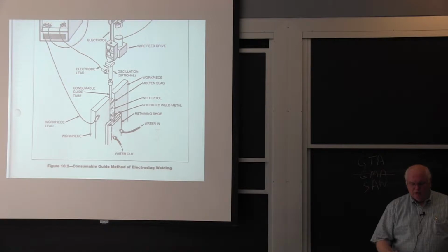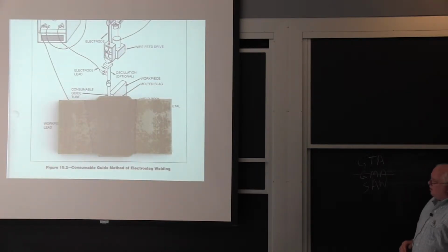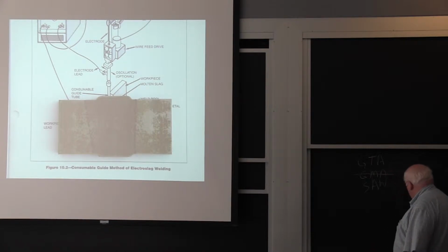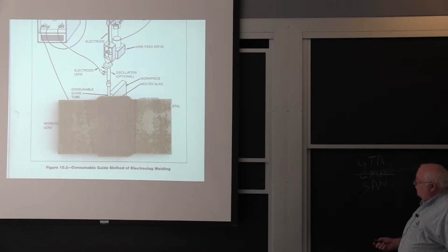It was a terrible weld, no fusion, but we found, wow, titanium is easier to Electro Slag weld than steel, so far as that goes. So at that point, the Navy classified everything, and I couldn't work on it anymore. But this is an Electro Slag weld in titanium that was made at Oregon Graduate Center, because even though MIT doesn't do classified work on campus, Oregon Graduate Center took a contract from the Navy, and this is 2-inch thick plate with an Electro Slag weld.